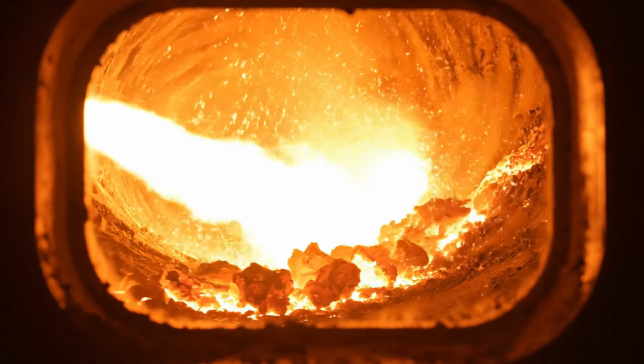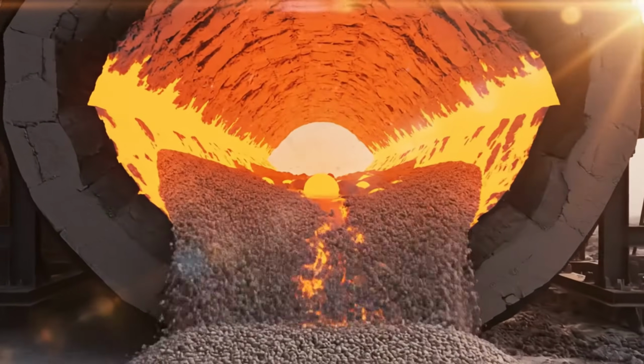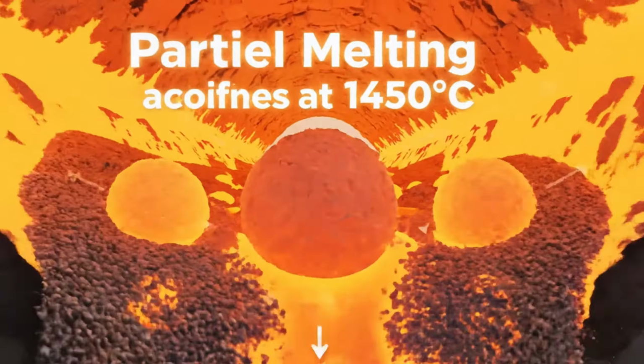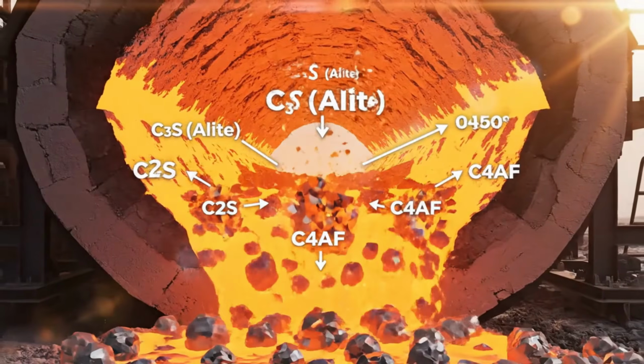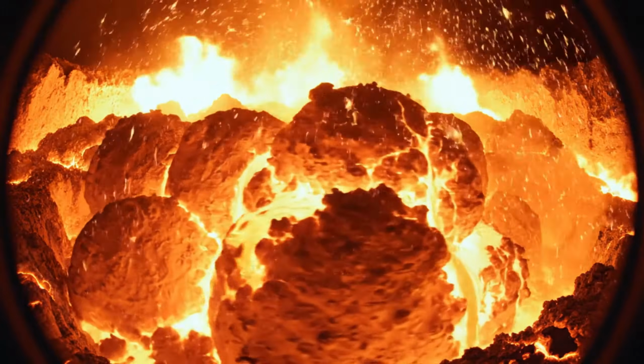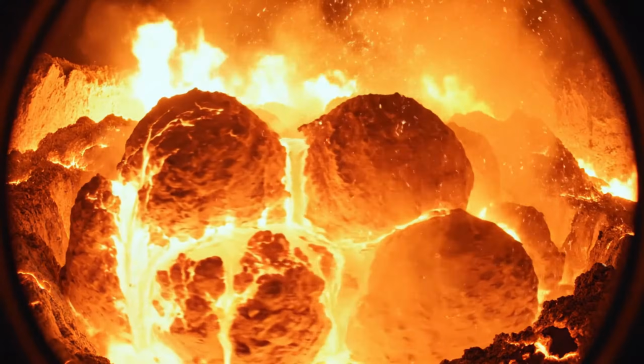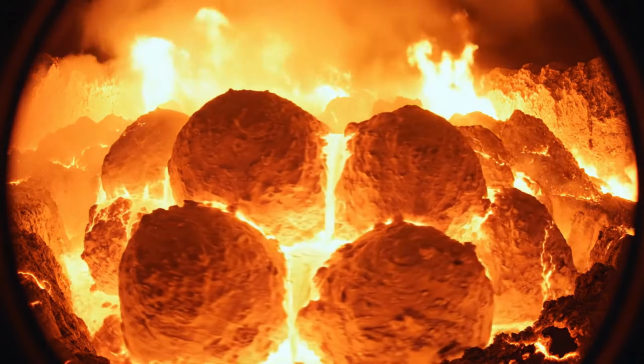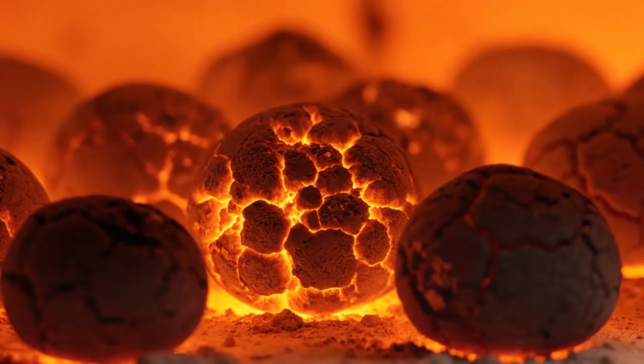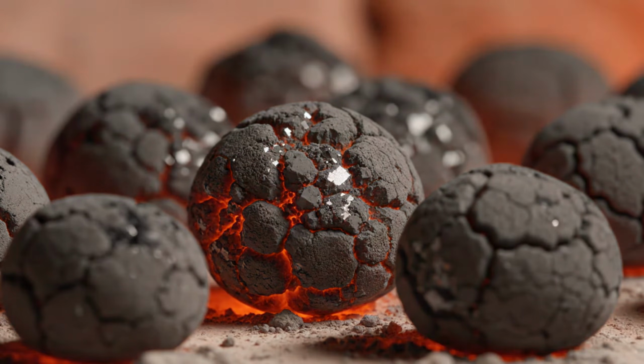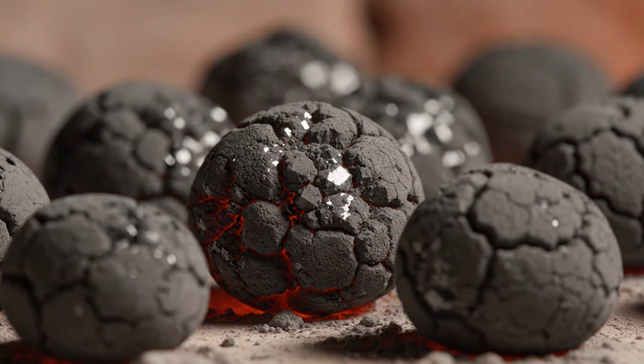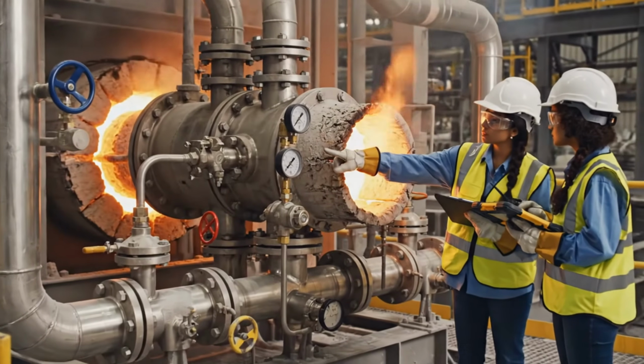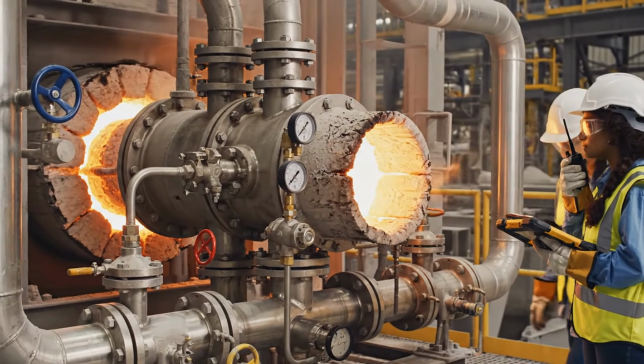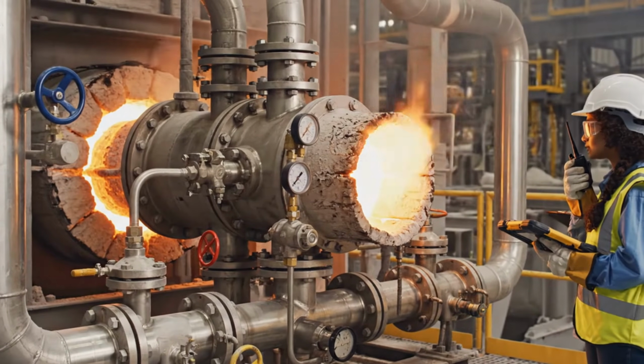This is where cement clinker is born. At 1450 degrees, partial melting occurs. Calcium oxide reacts with silica and aluminum. Clinker nodules form between 3 and 25 millimeters, their size and color indicating proper burning conditions. Modern kiln burners are engineering marvels, precisely controlling flame shape, temperature, and fuel efficiency.